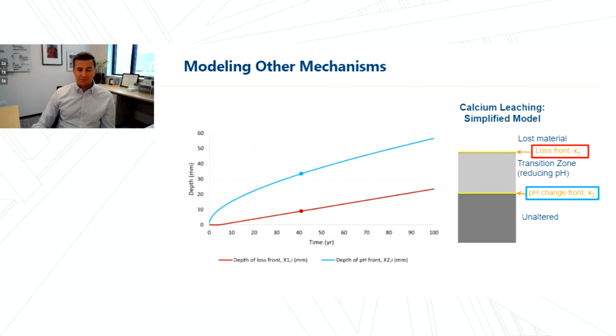If we extend this concept of modeling deterioration to other mechanisms, and the specific mechanisms here are not particularly important, but I'm using this to highlight that based on first principles, based on judgment assumptions and the experience required, we can come up with sound, scientifically driven relationships with time to make predictions for various deterioration mechanisms. In this case, the mechanism represented by the blue line has a relationship roughly in proportion to the square root of time. That represented by the red line is roughly linear after some buildup period.